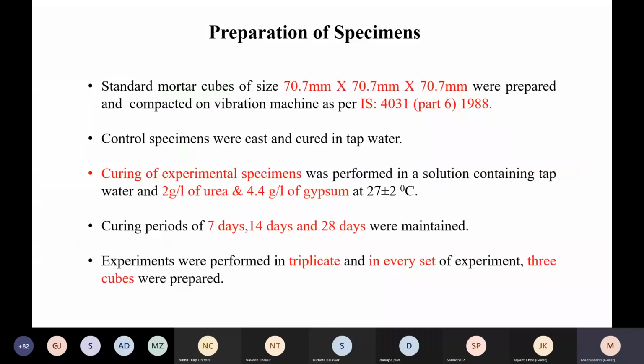Now, standard mortar cubes of this standard size were prepared and compacted on a vibration machine. Control specimens were cast and cured in tap water. Curing of experimental specimens was performed in a solution containing tap water and 2 grams per liter of urea and 4.4 grams per liter of gypsum. And why was the curing of experimental specimens done specifically in a curing solution? Because we wanted to ensure that till the end of the curing period, that is 28 days, the bacteria were supplied with, or rather not the bacteria, as I told you the bacteria are dead after the 7th day, only till 5 to 6 days they are surviving.